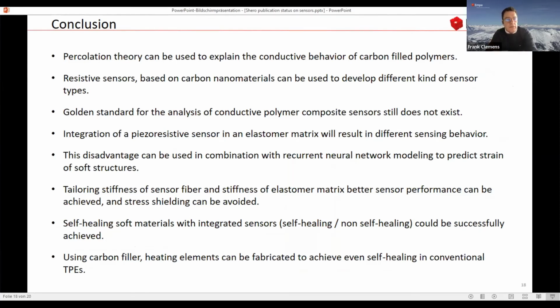By this, I would like to conclude, and I think you can read it by yourself. I will shortly say that percolation theory is important to evaluate and develop conductive materials, conductive polymers. You will also see this afternoon some more examples by Antonia when she gives her tutorial. You can also see that the gold standard for analysis of conductive polymer composites still does not exist. I think this must be improved quickly, because otherwise we have a lot of papers with no meaning. We really need to understand the sensor behavior better, and we need to be able to compare different sensors, which is almost impossible because everybody works with different strains. Therefore this must really be improved from my point of view.